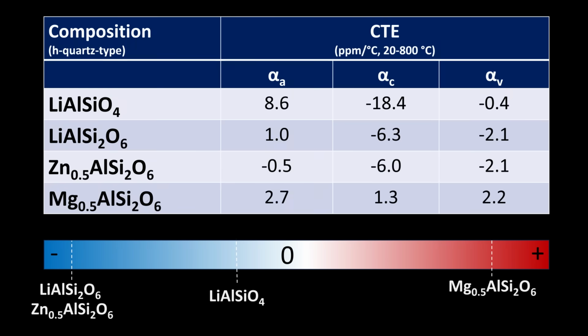This table sort of summarizes what I've just said. Here are the chemical compositions of the crystals discussed. These two columns show the linear CTE along the two important axes of the hexagonal crystal structure, and as you can see, the values are highly anisotropic. This last column contains the volumetric CTE, which quantifies how much a crystal would shrink in volume as a function of temperature, and as you can see, some of these do indeed shrink given that they have a negative CTE. So depending on the chemical content, you can make crystalline materials with a range of CTE values.